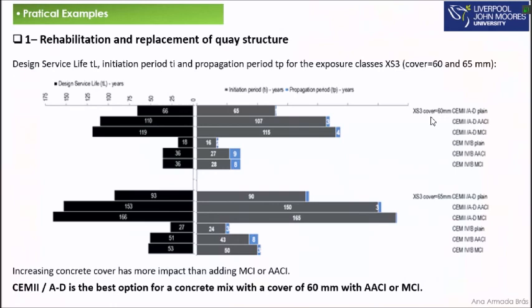We tested concrete covers of 60 millimeters and 65 millimeters. The first graphic that I show here is the concrete with 60 millimeters of concrete cover. The first concrete is the one with cement type 2 without any type of corrosion inhibitors, then with the corrosion inhibitors mixed in the concrete formulation, then corrosion inhibitor applied on the surface, and then again cement type 4 without, mixed, and applied on the surface.